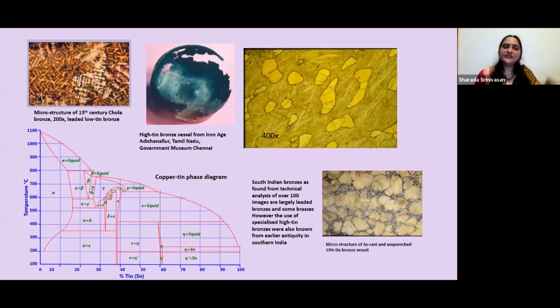Now, as I was pointing out, the Chola bronzes were leaded bronzes. And what that means in terms of the metallic structure is that typically a cast low leaded bronze has this dendritic structure, and the lead is what is called immiscible. It's not soluble in the solid solution of tin and copper. So it tends to segregate along the grain boundaries. But the problem is that when you keep adding tin to bronze, it actually gets more and more brittle. And bronze as such is not very workable.